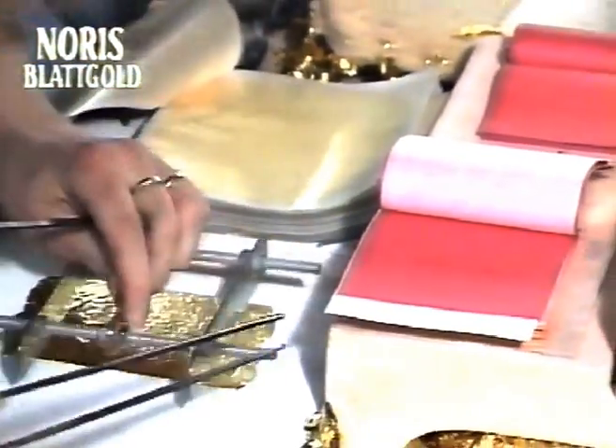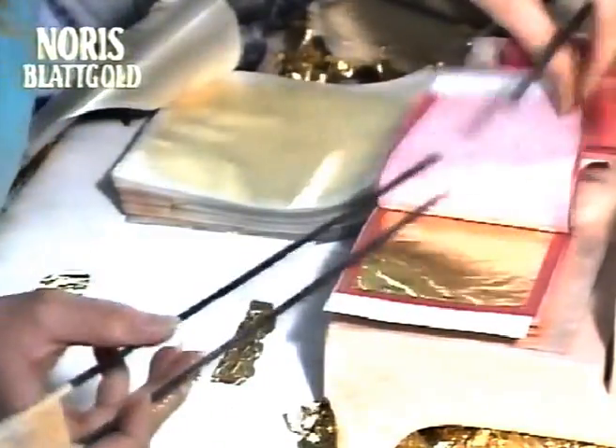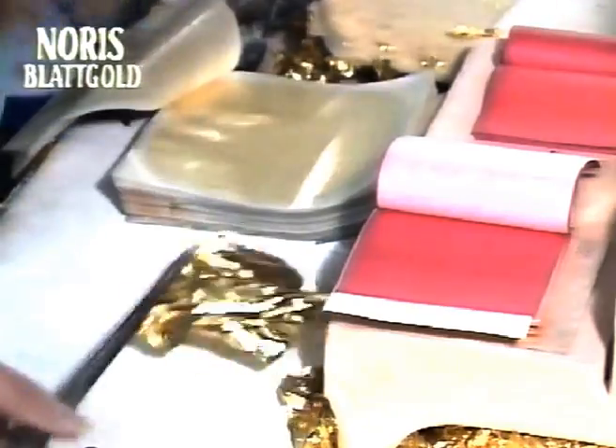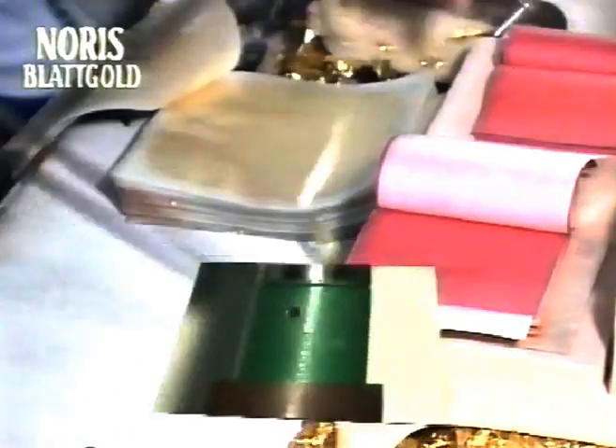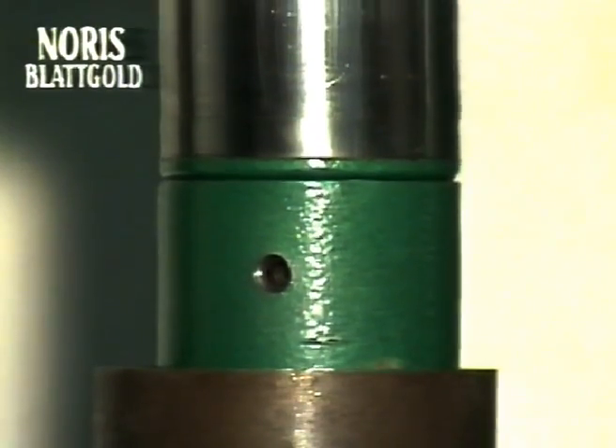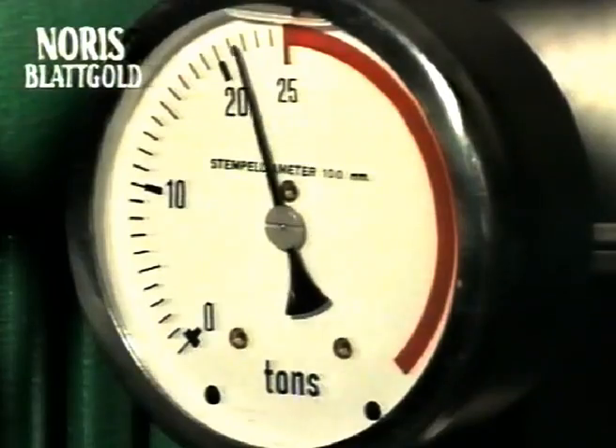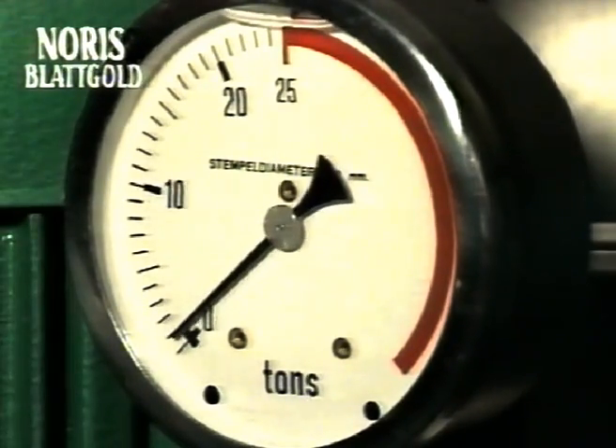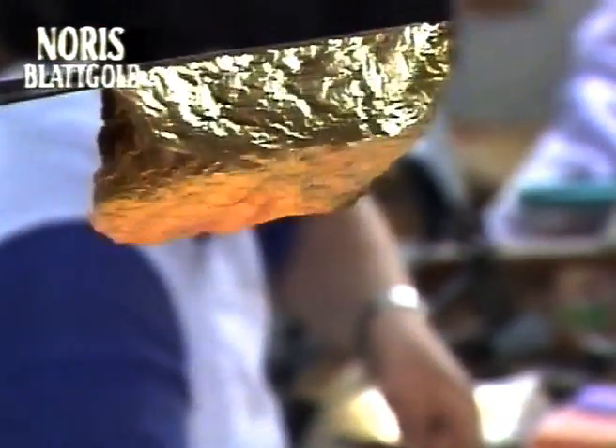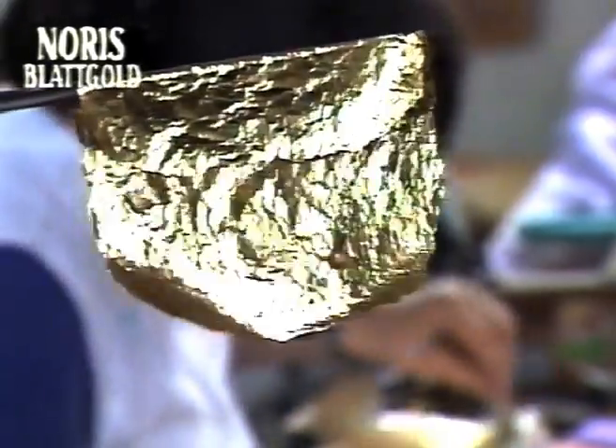The finished gold leaf with a thickness of 1/7,000th of a millimeter is cut into squares during a process of ongoing quality control. Leaf is custom produced in squares ranging from 65 to 140 millimeters a side. The gold trimmings are carefully collected and compressed under high pressure for later remelting. The ultra-thin gold leaf is put in booklets of 25 sheets each. Visual inspection against the light shows the leaf's high quality.